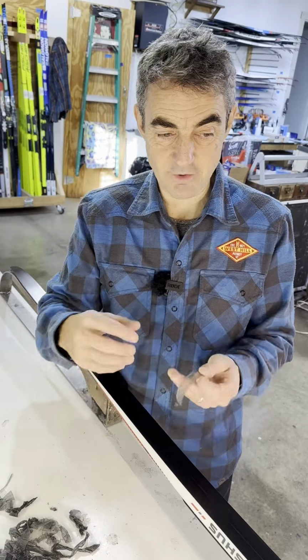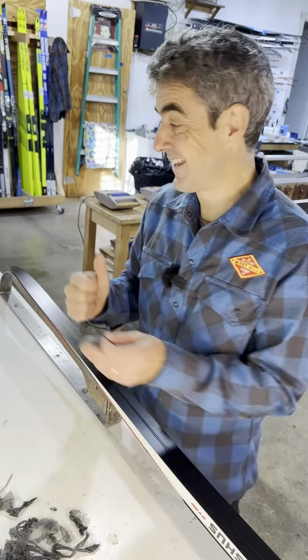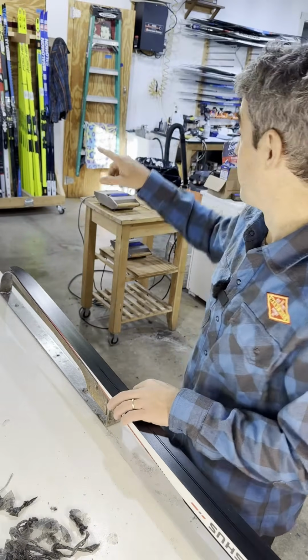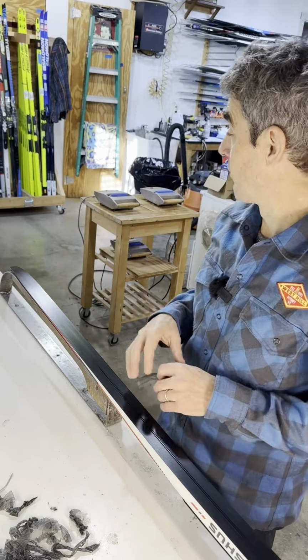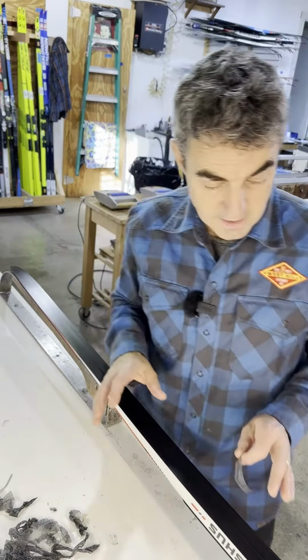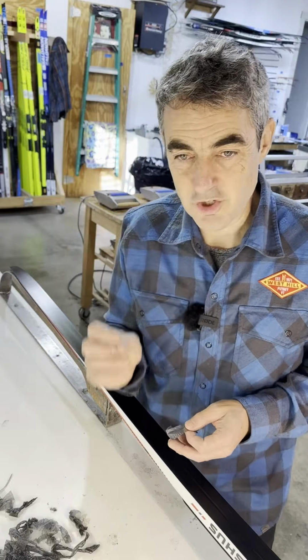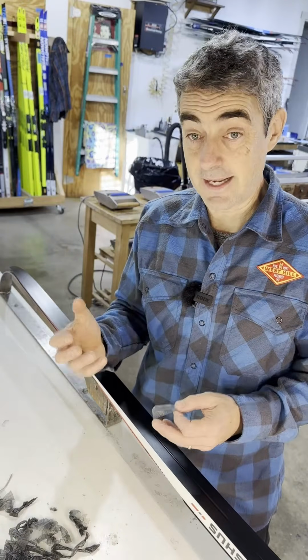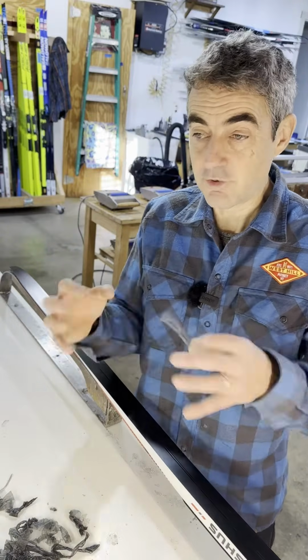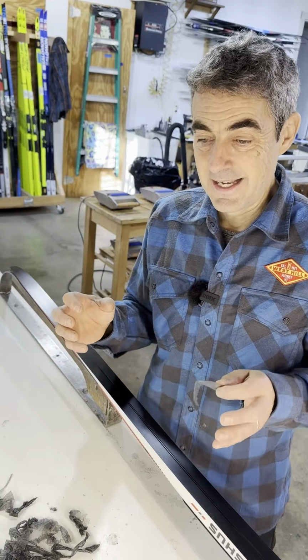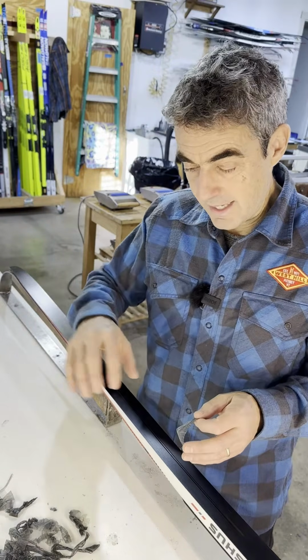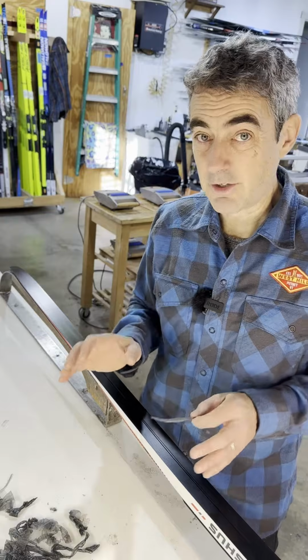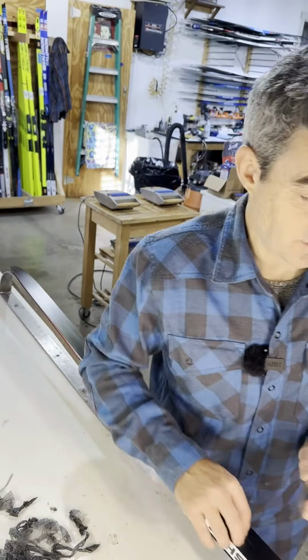It's not a super long-term process unless we're using the heat box. The heat box, it's a big cabinet over there. We can roll a whole rack of skis into it. That holds the wax in almost just a gelatinous state, a semi-fluid state, and it holds it there for hours, and it doesn't really excite the base, but things are warm enough that you get a little bit of filtering down, and we can very gradually put a lot of wax into the base.